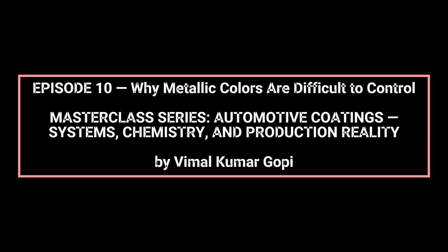At the most fundamental level, metallic appearance is governed by flake orientation. Aluminum or effect flakes act as microscopic mirrors. Their angle relative to the surface determines light reflection, brightness, flop, and color travel. Small deviations in orientation create visible differences between face, flop, and near-specular viewing angles. As a result, metallic colors amplify process inconsistencies that would be visually invisible in solid colors.